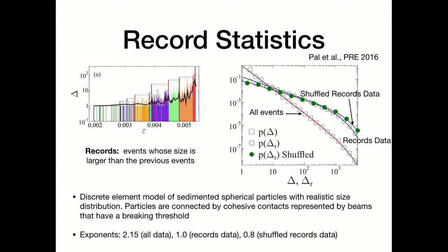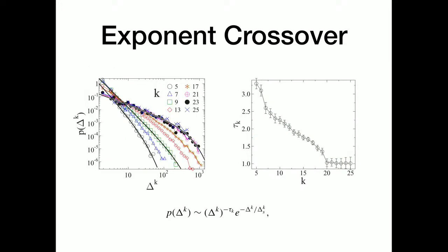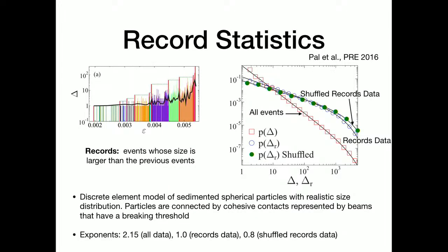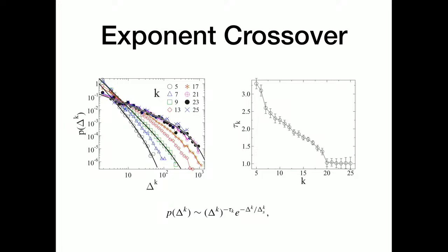Now, the other thing that they use this concept of records for is to come up with what was earlier the strain dependent exponent. We didn't know what ways we could mark as boundaries. Now you have clear boundaries, record 1 to 2, whatever is in between, you can do the statistics of that, and you can see how these exponents evolve with the applied strain. So what was seen is that the x-axis is the record index, and as you go along, you see that the exponent, so maybe we should look here first. So these are the record indices, 5, 7, 9, 13, like that, and for each of them associated subsequences,